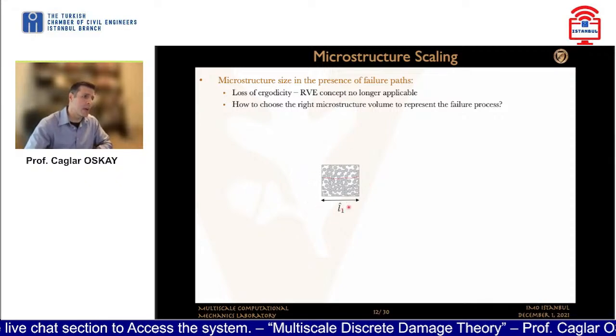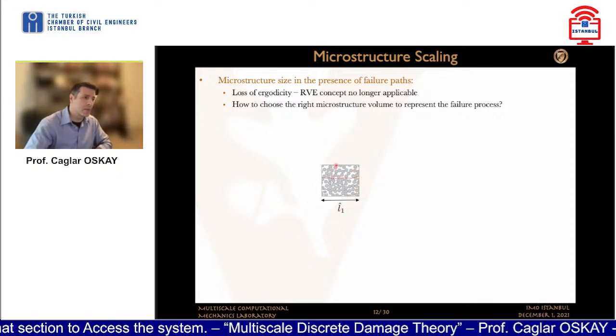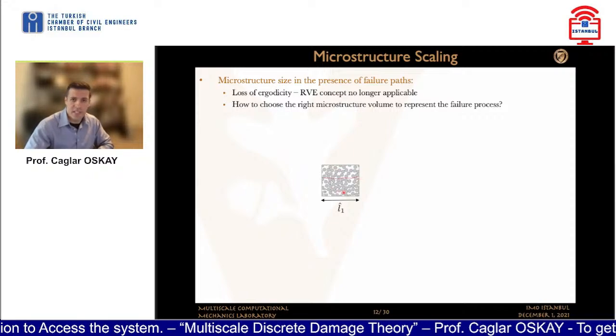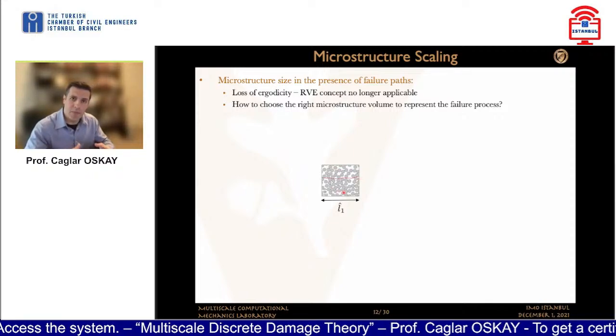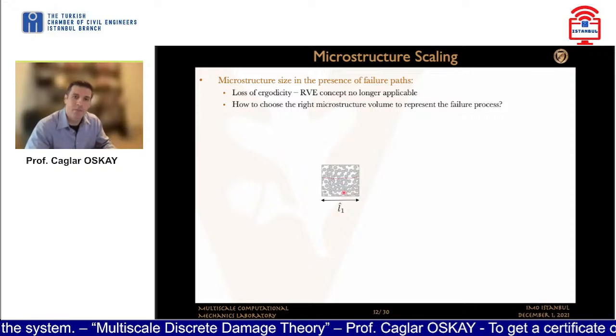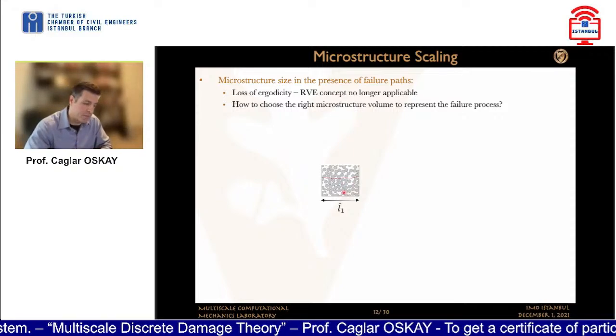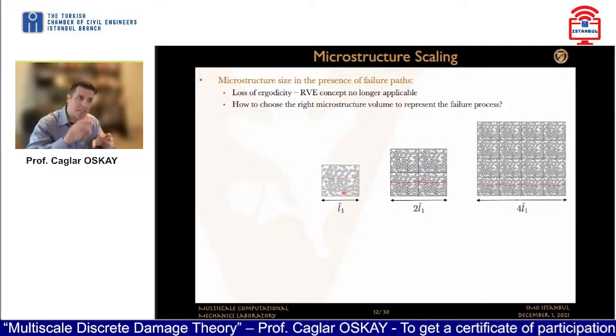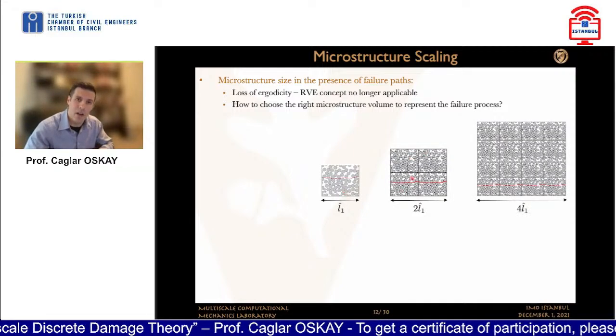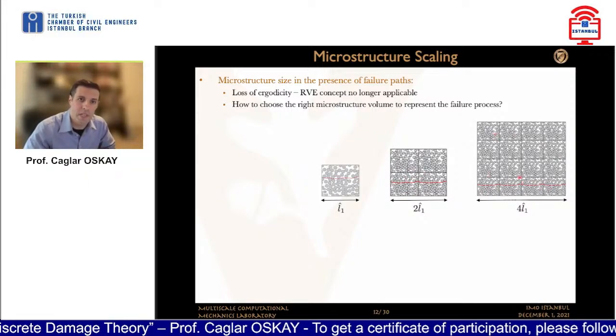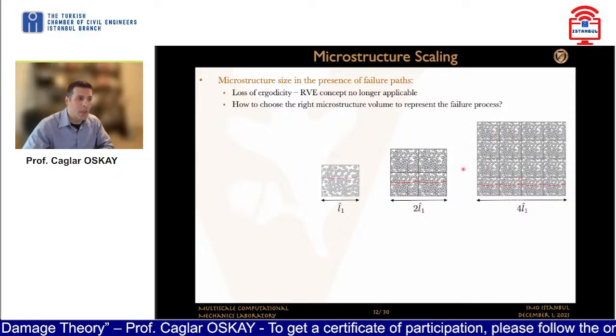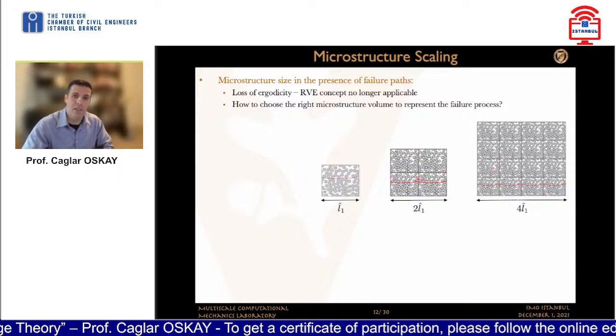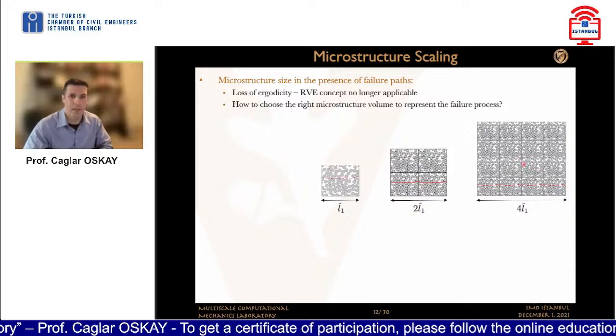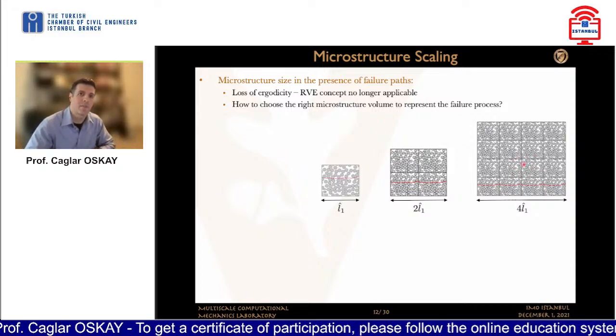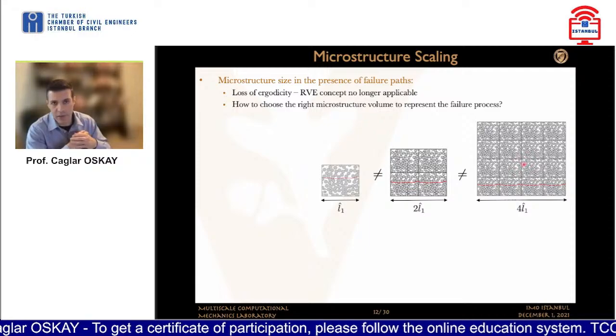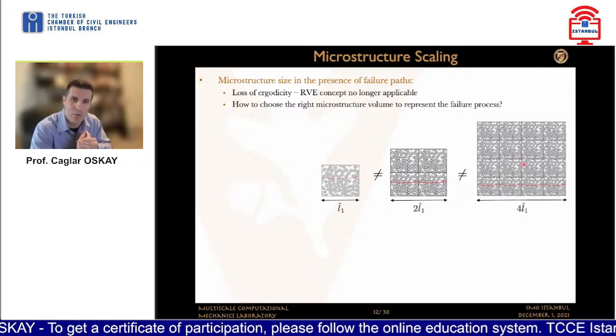So consider a microstructure and a fracture path that we would like to incorporate. And the microstructure itself is a reasonably sized microstructure, which represents the statistics of the geometry of the morphology correctly. Now, you can double this in size in two directions, make a little larger microstructure, or quadruple this and create another microstructure. And the expectation is that they are supposed to behave more or less the same way, because there's no new information embedded into that structure. But it turns out that they don't provide you the same response.